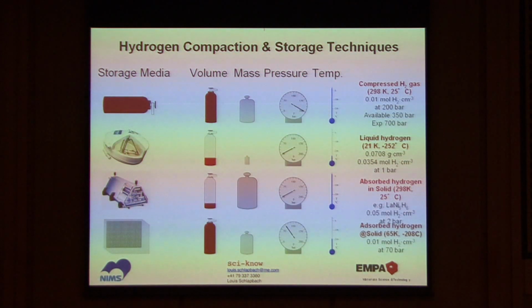So an overview about compacting techniques. We have heard about high pressure, typical tanks of 200 bar, high pressure tanks with aluminum inliner with carbon fiber reinforcement, up to 700 bar or 70 megapascal, working at room temperature.